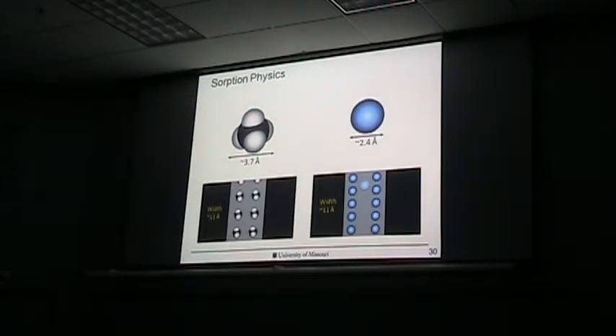And the same here, if you look at, for example, an 11 angstrom pore, these are the main pores we have in our system. For methane, you see you can get 2 layers, and for hydrogen, you can have actually 1 layer on the left, 1 on the right, and here in the middle, this is what I call a 3rd layer. So it's not really as dense as directly on the surface, but it's still denser than the gas phase.